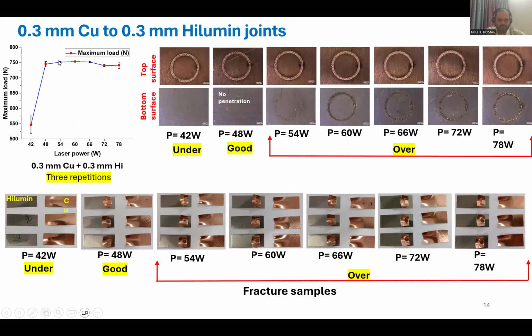And this is a similar example. I have varied the power from 42 to 78. The top sheet is copper and the bottom sheet is the same as the previous one, 0.3 millimeter Hilumin. Here the strength is higher because the material itself is strong. Copper is very strong compared to aluminum, which is why we are getting more than twice the strength compared to aluminum.